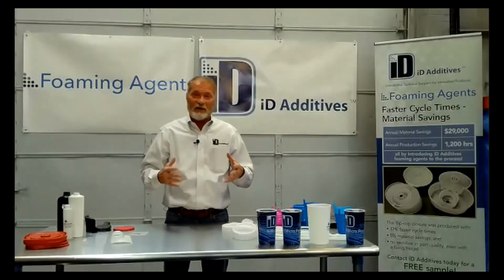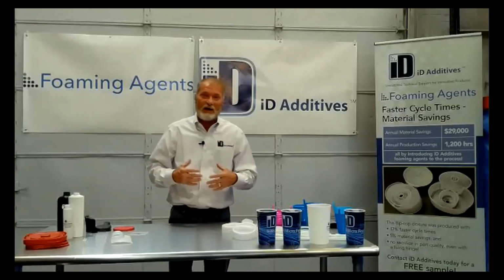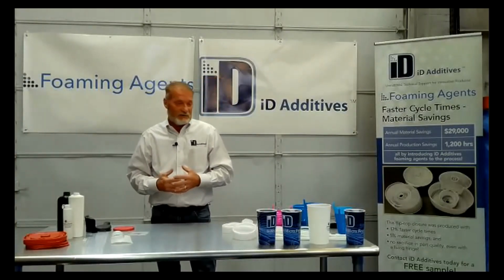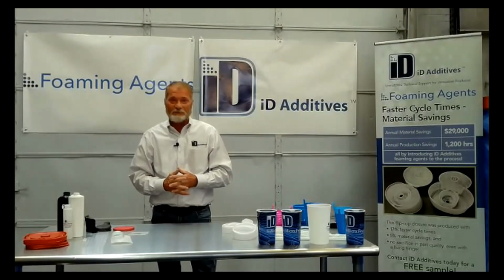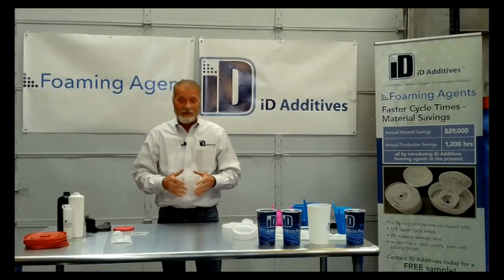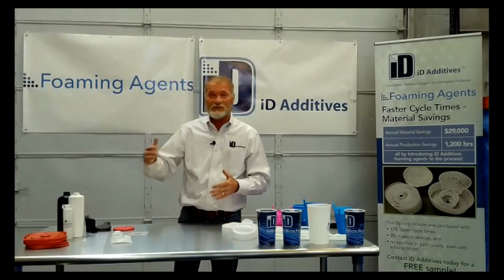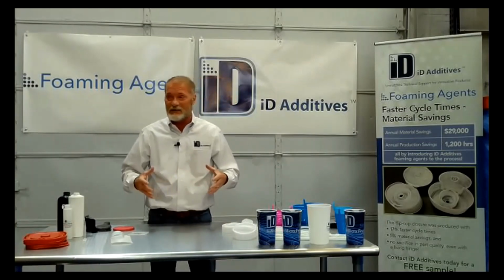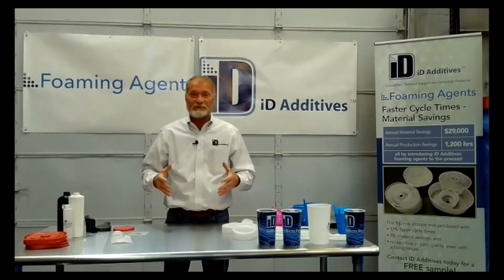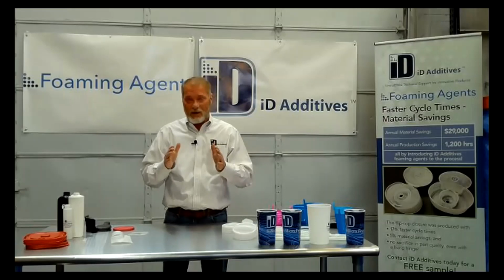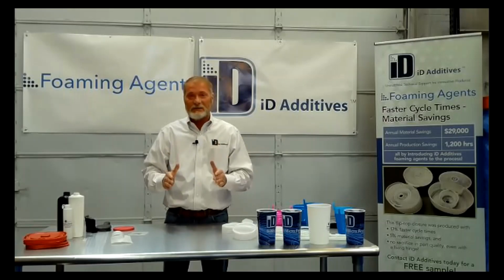So the amount of foam you put in and the velocity you use, that's going to determine how much foam you can put in it, really. The faster you go, the more foam. And there's a certain point that no matter what, you start adding foam and it'll start pushing it to the surface because you're really inundating it with bubbles. So you have to use the right amount you need to get where you want to be.